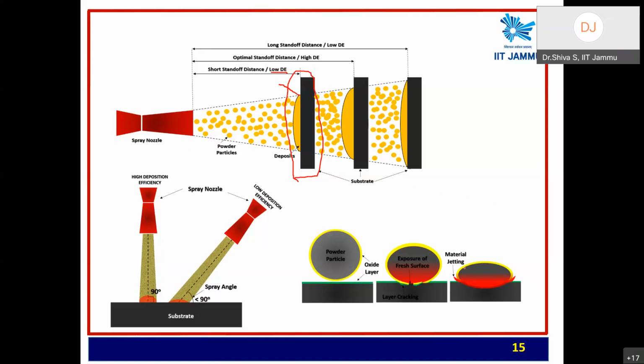So this is the difference. If the powder particle starts breaking, then obviously the required material property will not be met. And when we come to the next level, this particular distance, yes, there is no bowing effect. This reverting back or rebounding effect is called the bowing effect in cold spray. And if there is not much bowing effect and the impingement is sequentially hitting the surface, what happens is maximum deposition, almost 99.9%, just like your wire. This is one of the primary setups where the maximum deposition efficiency will be achieved.